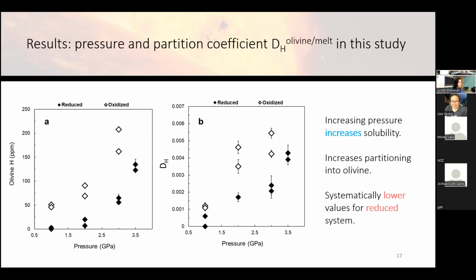And we also see an impact on the partition coefficient, which is simply the ratio of hydrogen in olivine to melt. It also seems to systematically increase for both the oxidized and reduced experiments, holding all other factors constant. So that's exactly as expected. Pressure increases solubility.